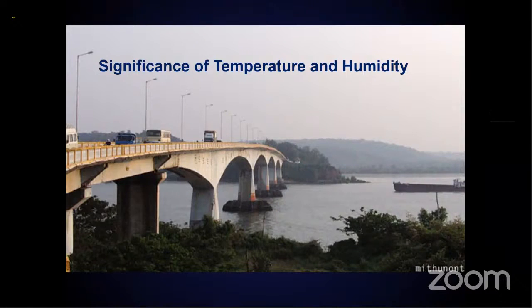This particular structure was in a highly corrosive region, and because of the aging and deterioration process, the structure was highly degraded. So because of the degradation, extensive retrofitting was done. Although the structure is already in the worst situation, in a highly corrosive zone, highly humid and with quite high temperature, the choice of retrofitting is also important, and whenever you're doing a retrofitting scheme you have to take care of temperature and humidity.